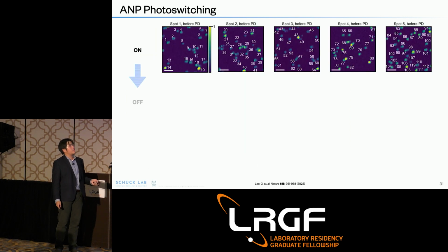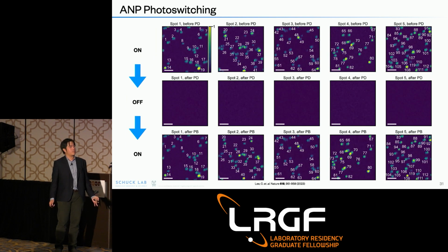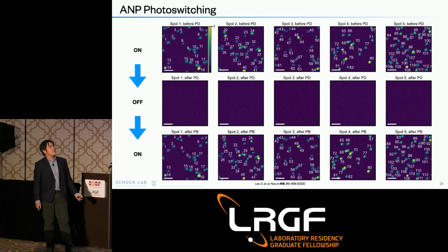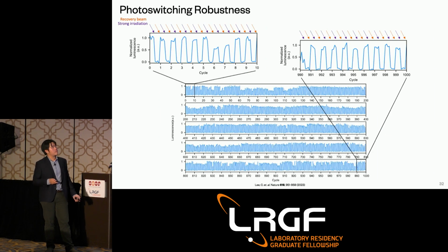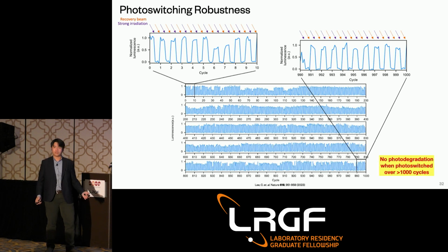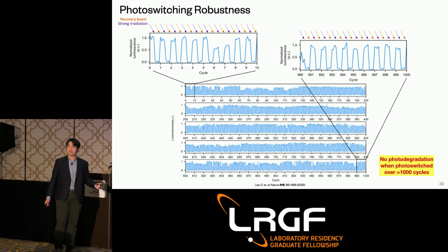And if you repeat this over 100 different particles, you can see that the behavior more or less stays the same. And additionally, the photo switching robustness that we see in this nanoparticle really holds for about 1,000 cycles, meaning that the quality of this material doesn't really degrade when you're cycling them about 1,000 times.